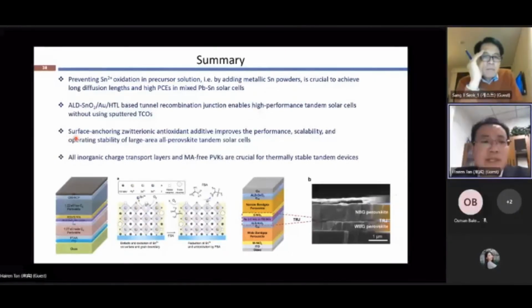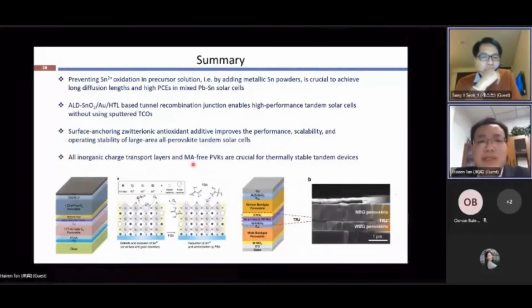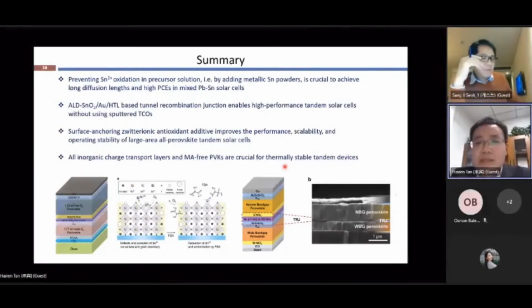And by using this surface-anchoring zwitterionic additive, we can improve the performance, scalability, and also the stability of the tandem devices. And at the end, we show that by using all-inorganic charge transport layers and methylammonium-free perovskite absorber layers, we can get thermally stable tandem devices.